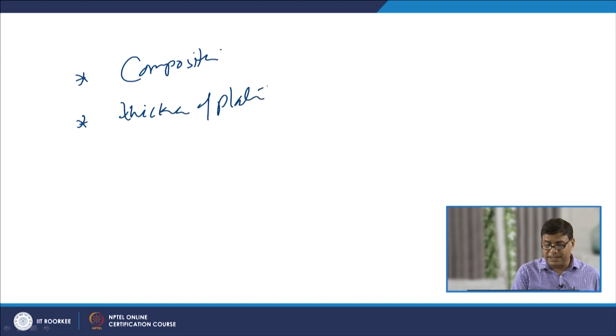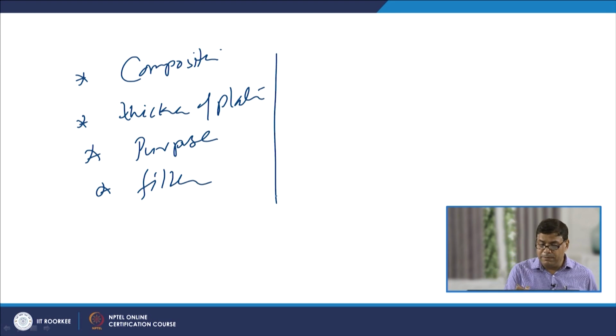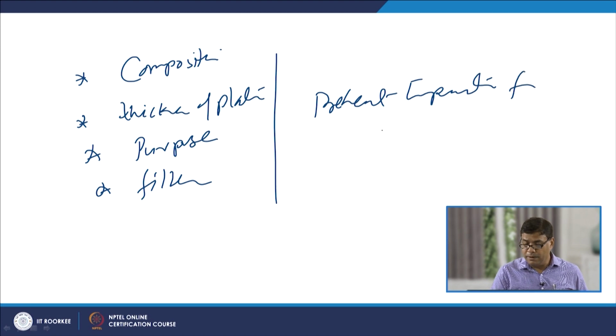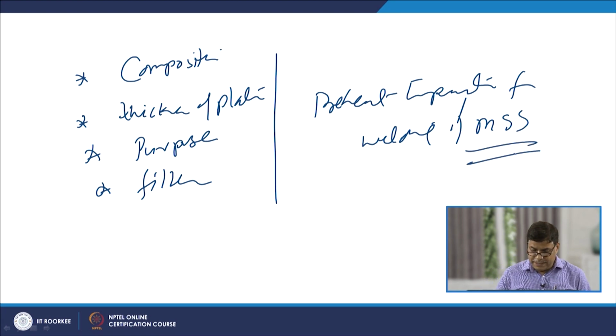The value of the preheat to be used will depend especially upon the carbon content present in the steel. So, we will say that the composition, the thickness of the plate or the section which is to be joined, the purpose for which the weld joint is to be used, and the filler which is being used, these are the 4 important factors that will be affecting the preheat temperature to be used for welding of the martensitic stainless steel. So, now we will see that as per the thickness, composition and purpose, different preheat temperature values are used.